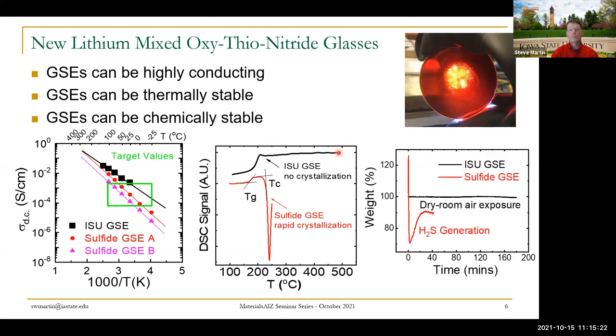But also through this compositional optimization process, we can make some mixed oxysulfide glasses where we dramatically improve this chemical stability. And this is a plot of a typical sulfide glass, a lithium sulfide, silicon sulfide glass. That reacts immediately with air and forms hydrogen sulfide, which is toxic, of course. Our ISU compositions, I'll show you some in a moment, lithium sulfide, silicon sulfide, phosphorus oxide, these oxysulfide glasses, you see are stable over many hours in air, which is a real advantage in processing and lowering the cost of the processing of these glasses.